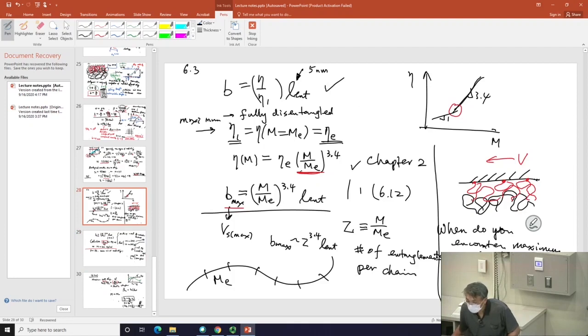It's better for you to go all the way back to the formula at the top. There, which is actually the origin. It's more original than what I further deduced later. So even for a polydispersed sample, this formula, the top one, is accurate. In other words, B is proportional to eta.